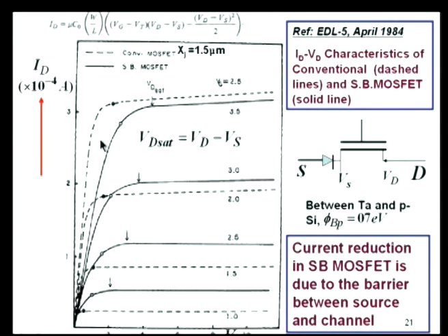But ideal means the source and drain diffused. In the metal semiconductor contact, for the same current, you have to apply higher voltage, because part of the voltage has gone to this V s. So, that is V d minus V s is the one. So, you can use the same equation that you use for the MOSFET. So, they did get MOSFET action, but lower currents, or you apply more drain voltage for that. This is due to the barrier between the source and this channel, this is the thing that they observed.